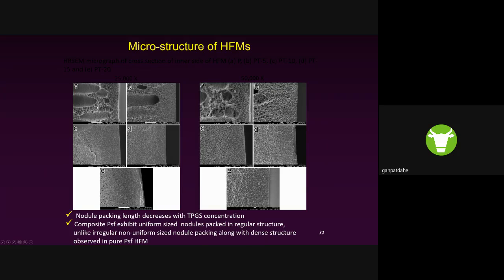So you can see here this is the pure polysulfone. Then this is the 5% TPGS, and as you can see, the packness of the structure decreases with increasing content, and the thickness of this dense structure decreased, and you can see more porosity here in these high resolution images.